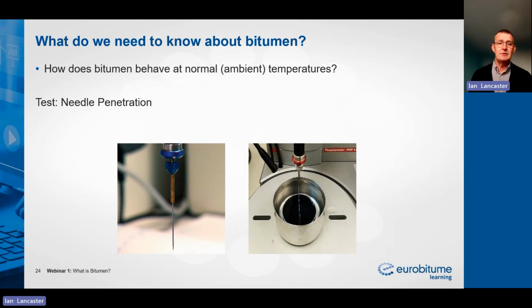So what we do is we produce our sample of bitumen that you can see here. We condition that down, firstly in air and then in water, to 25 degrees Celsius. Then we bring a needle to rest exactly on the surface of the bitumen. We can't allow the needle to penetrate, and we can't allow the needle to be above the surface of the bitumen. Otherwise, we get a result which is false and is not valid. So we bring the needle to rest exactly on the surface of the bitumen.